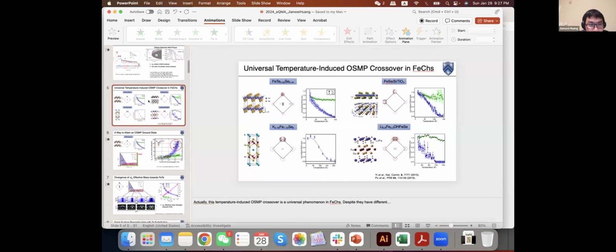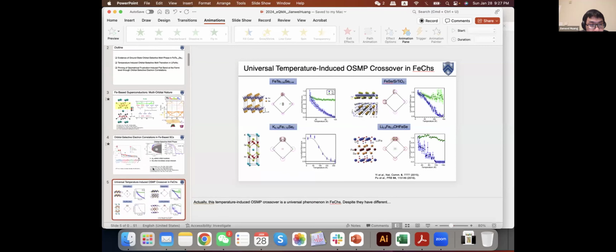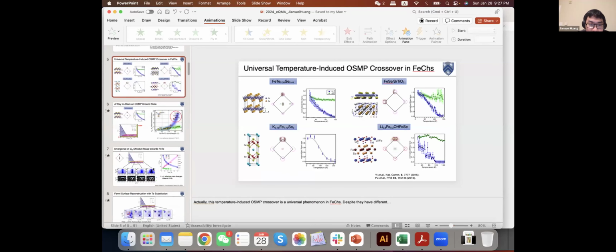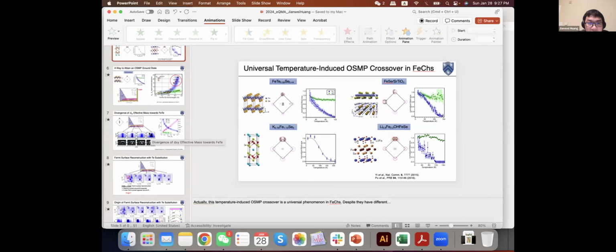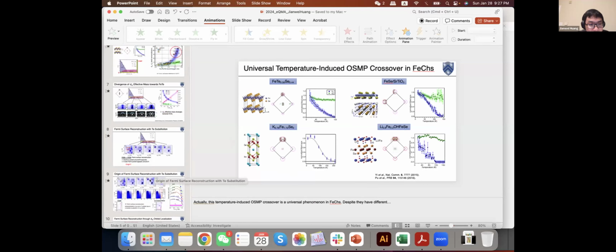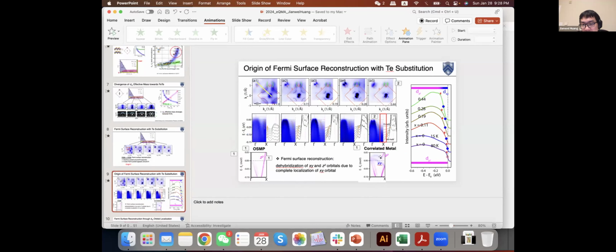For the second question, from the experimental data, I think it's a gradual transition, but I'm not sure whether the calculation can produce a gradual transition in this case. But I think if we tune these correlation strengths, I suppose this hybridization gap can gradually shrink. I don't know. From the calculation, it seems to be a very sudden change, while from the experiment you can see there's a gradual change.